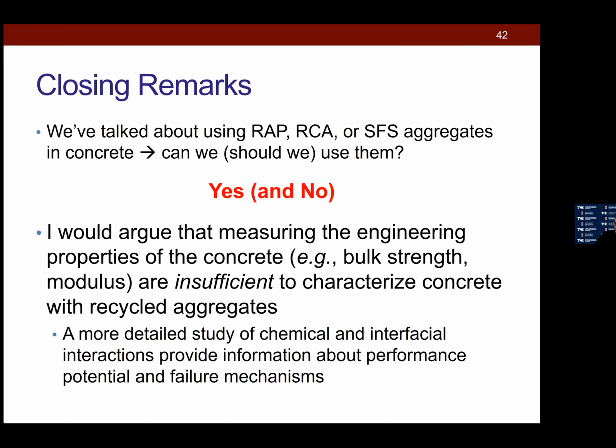What is the time scale at which aggregates will draw water from that free available water? I'm using dolomitic limestone with 3.8% absorption, which is pretty high. Do you have a time frame or literature on that? Yeah, there have been a handful of studies. As I recall, things like limestone, something without too high of an absorption capacity, is usually a handful of hours, maybe up to 12 hours. And again, things like RCA is probably going to take 24 to 48 hours, if not longer.